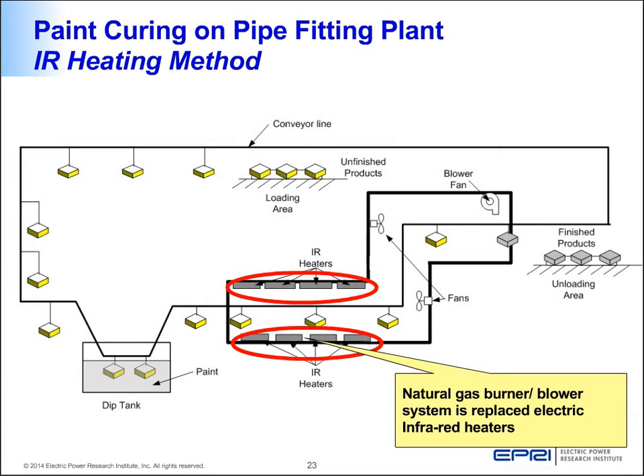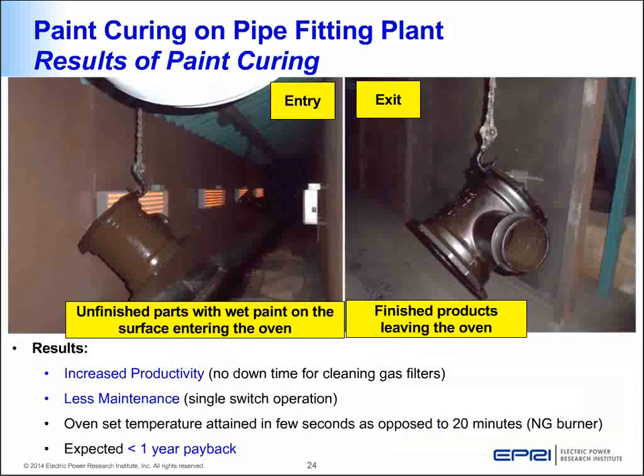the natural gas oven was shut down, and in the existing space, without adding any additional equipment outside, just within the existing footprint, they installed four on each side to impart heat from both sides so the paint could be cured. With just 8 heaters, they were able to get the required curing of the coating. The process did not shut down because of maintenance reasons, and productivity was maintained. And the customer had less than 1 year payback for this particular application.